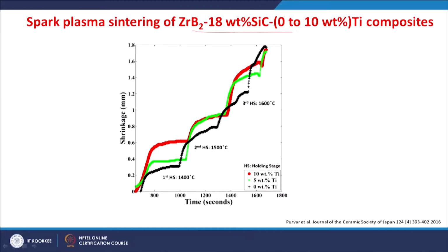So, these composites were prepared by spark plasma sintering. First, the powders of zirconium diboride, silicon carbide and titanium were taken and mixed in a proportion of zirconium diboride with 18 weight percent of silicon carbide, with titanium amount varying from 0 to 10 weight percent. So, these powder mixtures were kept in a die and then subjected to spark plasma sintering. So, spark plasma sintering gave a decent density of more than 98% density. So, we can see the spark plasma sintering result, the shrinkage versus time.